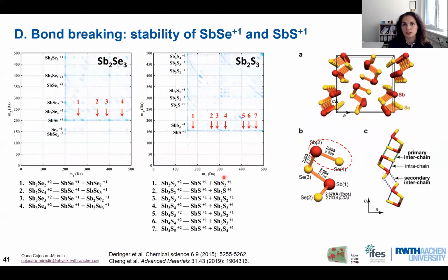To show you the implication in terms of atom probe experiments, I show you here how the bond breaking takes place for two compounds, antimony selenide and antimony sulfide. And here I show you the correlation histogram. Many of you are familiar with this correlation histogram. It simply gives you the distribution of the multiple events in a 2D map. And we see that we have many dissociation tracks available on this map.